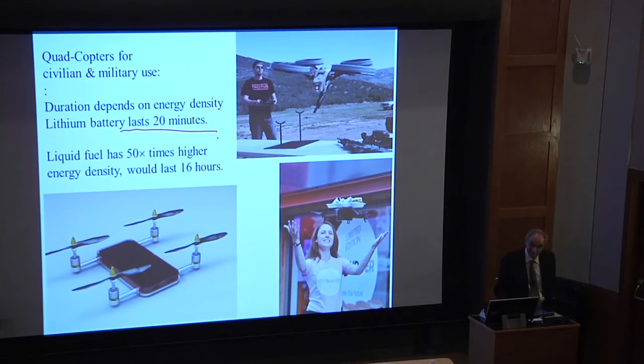However, suppose you have an application where you need to stay in the air for very protracted periods of time. The amount of time you can stay in the air depends upon the energy density of the energy source. A lithium battery obviously has much less energy density than liquid fuel. If you have a liquid fuel and you just burn it to make the heat, then the energy density is 50 times higher than a lithium battery. And so instead of lasting for 20 minutes, it would last for 16 hours.